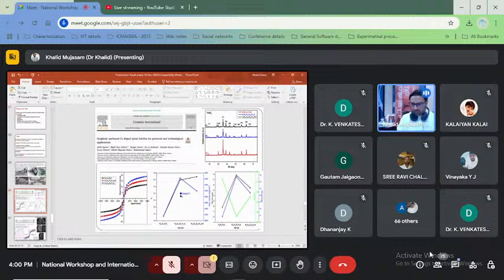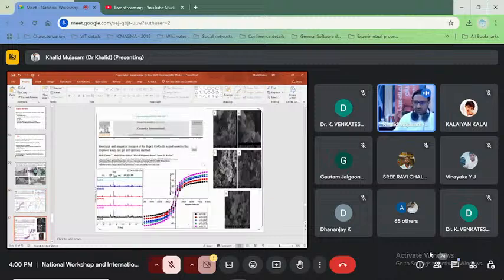So this is one part where we used graphene, cerium-doped spinel ferrite with graphene. You can see that overall the magnetic properties were not much; 20 EMU was achieved. In the next part, you can see the cerium-doped material, but there is no graphene. However, you can see the saturation magnetization has gone above 40 EMU.